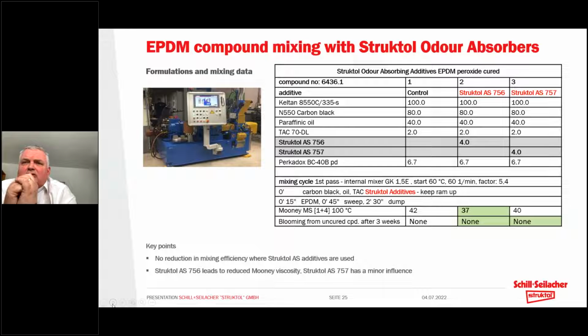And you can see right away the effect on the Mooney viscosity. We're measuring really small. So the lubricant product, compound number 2, has a reduced Mooney viscosity, 5 points lower, with a smaller reduction when we have no additional process additive effect. So we went down only a couple of points in Mooney viscosity. It's important that we know that these additives remain in the compound. We know the VOCs is a surface action, of course, a diffusion action, but we don't want the lubricant or the active components of our odor absorbers to also migrate to the surface. So we assess that there's no blooming in the uncured compound with or without the additive. So we have good compatibility in the rubber. Next.